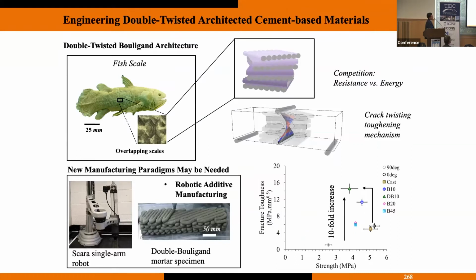So it's an interfibrillar bundle of fibers. So you have fibers and then you have interfibrillar matrix in between. For every orientation, there's a bilayer orientation. And it turns out that this layer essentially arrests the crack, where the other one makes it harder for the crack to propagate, because as you twist the crack, it's harder to shear a crack than to open a crack, if that makes any sense.